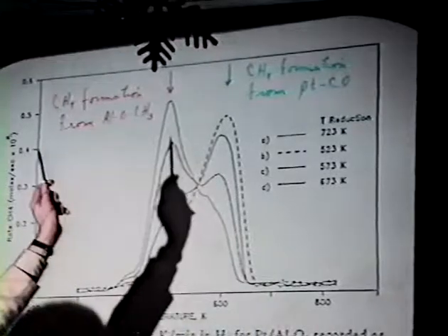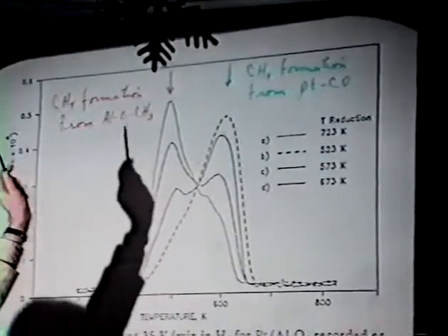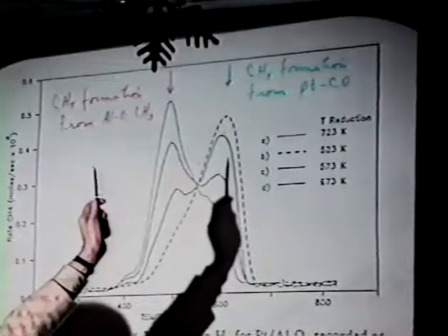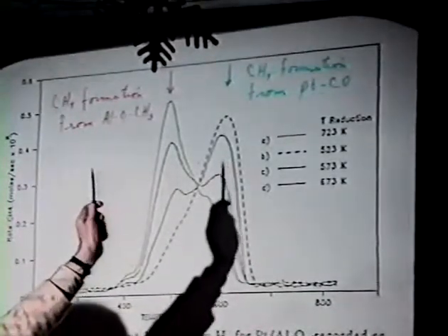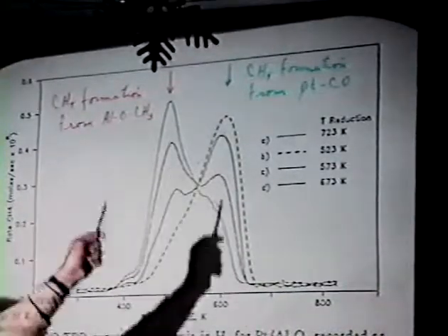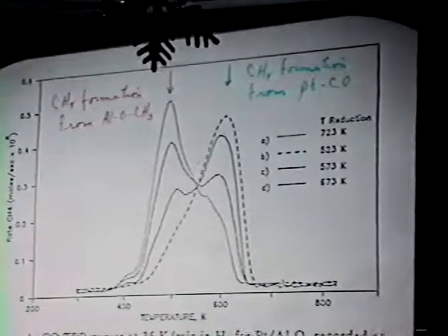And what's interesting is that you hydrogenate this species, which is identified and seen in the infrared, at a lower temperature than you hydrogenate this species, which originates from CO on the metal. And so that suggests that, in fact, this route might compete with this route. And so I actually think now probably the better way of looking at both the platinum on the TiO2 and the platinum on the L zeolites is a different kind of bifunctional reaction, and it isn't telling us anything about electron transfer. So wipe all of that off the slate, and let's go try something else.